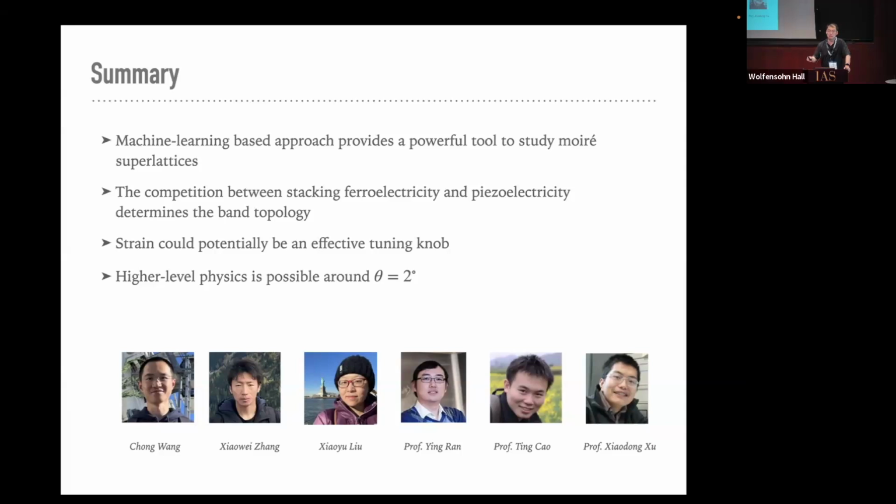Oh yeah, that's basically the whole point of that paper. One thing is simply to make the hopping smaller, as you said, right? But the other is because of the d orbitals. If you think about dxy and dx squared minus y squared, they have a very anisotropic shape. So when you consider their hopping, the hopping itself is highly anisotropic. And even though the nominal t in front of it can be very large, because of this anisotropy the band can be made flat, as we showed. The band structure I showed there is just a very simple tight-binding calculation. You put the d orbitals in there, and the flat band just comes out.